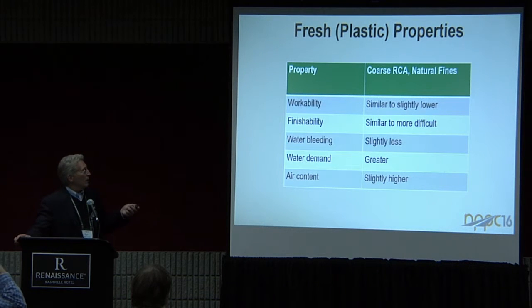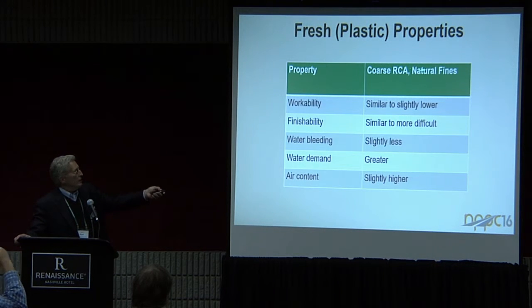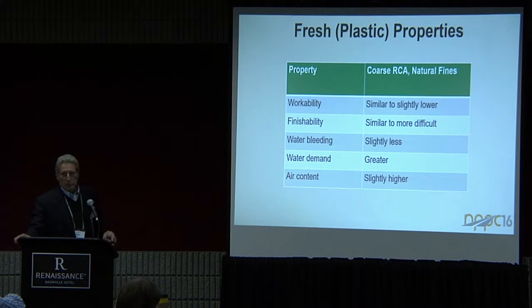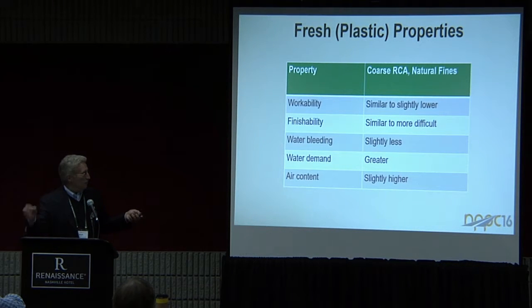The properties of our mix made with recycled materials are going to be, again, depending upon what you're using, clean of all the old mortar, it might be pretty close to the same as you have with a natural aggregate mix. If you have a lot of reclaimed mortar, you probably have a little less workability. Finishability can be similar to much more difficult. Tend to have less water bleeding, particularly if we have some fines in there. They tend to kind of clog up the capillary pores for the water to come through. So less water bleeding, more water demand, as we talked about before, and our air content might be a little bit higher because of the entrained air that's already present in the reclaimed mortar.